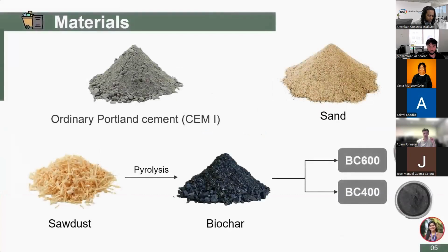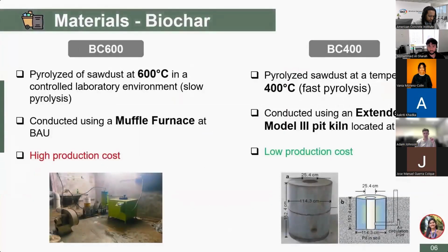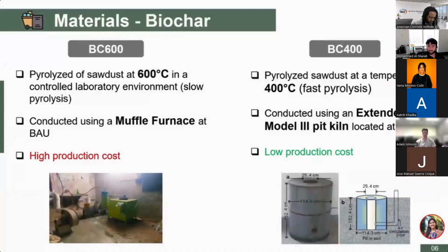These are the materials that we used in our study. Two types of biochar were used, BC400 and BC600. BC600 was made at 600 degrees Celsius using a lab furnace, which makes it more controlled but costly. On the other hand, BC400 was produced at 400 degrees Celsius in a simple pit kiln, making it much cheaper and easier for field use.